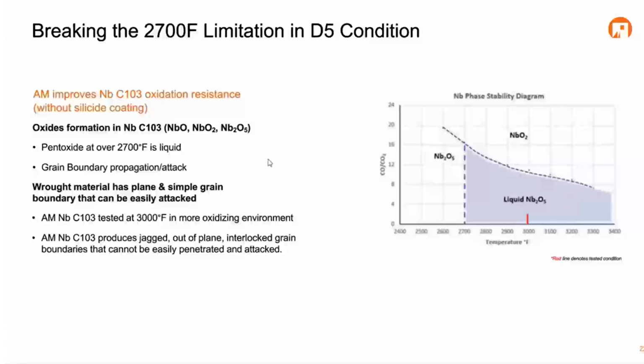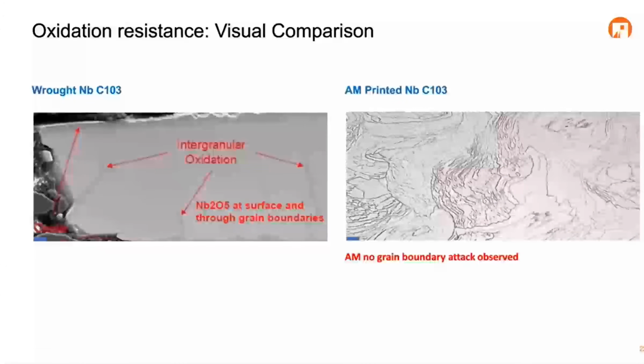When we look at the grain boundaries and why we're seeing better oxidation resistance, I kind of equate it to a racetrack. When we look at a drag strip with straight planar grain boundaries, because oxidation is a diffusion type mechanism, oxygen from the atmosphere surrounding the material is able to penetrate along these grain boundaries at really high rates, forming these pentoxides and liquating and degrading the strength of the material quite readily.